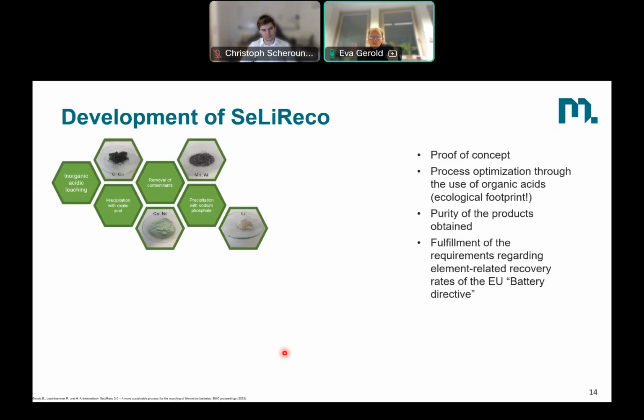Well, and now I would like to tell you how we get to hydrometallurgy here at the Chair of Non-Ferrous Metallurgy. And actually, we developed a completely inorganic process at first. It's called the SeLiReco process. We started with an inorganic acidic leaching, so very standard. Then we have some organic acid already there, like with the precipitation of oxalic acid, we recover cobalt and nickel as a mixed oxalate. We removed some contaminants, and at the end we also recovered lithium as lithium phosphate, via precipitation.